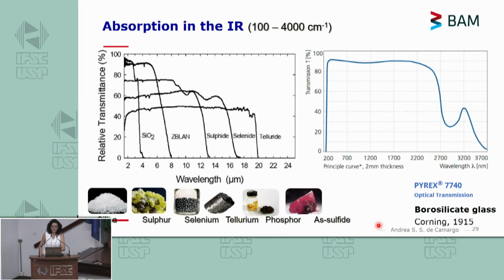We're not going to go into these details because we don't have time, but what I can tell you is that by characterizing the absorption in the infrared, you can have a good idea of what's the best glass for your optical application. So this is the curve here for the Pyrex glass developed by Corning. Everybody has heard about Pyrex, right? It's used for kitchenware, basically. Also has some specific applications. It's a borosilicate glass invented in 1915. And here we have the relative transmittance for different glasses like silica glasses. ZBLAN is a fluoride glass, sulfide, selenide, telluride, chalcogenide glasses. Right? So you can see that you can get pretty extensive transmission, but of course the intensity will drop in the infrared.